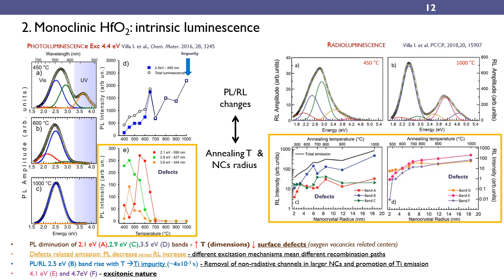Except for the blue band, the other visible bands are confirmed to be related to intrinsic defects, but under ionizing radiation, their increment is due to a different efficiency during the transport of carriers toward the emitting defect. In large nanoparticles, the transport is the most efficient, thanks to the removal of non-radiative centers that can compete during the transport stage of the radioluminescence mechanism. For this reason, the radioluminescence increase is expected while the nanocrystal size and the annealing temperature rise.